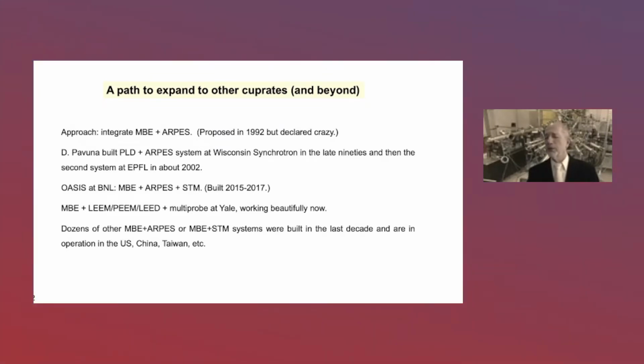Nevertheless, Davor Pavuna, who is regrettably not listening to this, followed this suggestion, and in the late 90s built a PLD system integrated with ARPES at the Wisconsin synchrotron. And then a few years later, he built a tabletop one at EPFL in Lausanne. And they produced some interesting in situ ARPES data on LSCO, for example. Now, our BNL proposal was finally funded in 2014 or 15. And then within a couple of years, we built it, and it's working beautifully. There is an MBE machine and ARPES and STM all coupled together.